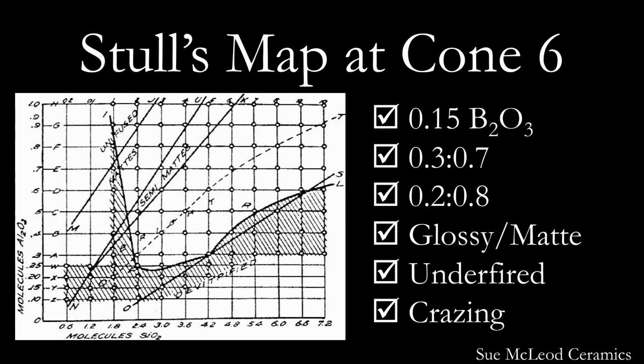The results from this research show us that we can use Stull's map to accurately predict glaze behavior at cone 6. Stull tells us if our glaze will be glossy or matte, crazed or underfired. This leads me to believe that Stull's map could accurately be used to predict glaze behavior at any temperature, provided that your glaze is properly composed to melt at that temperature.